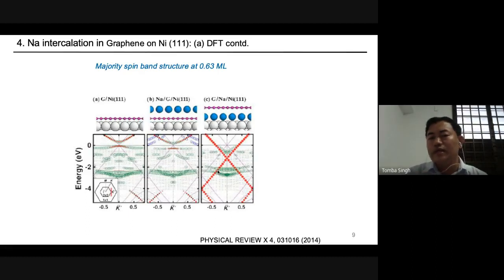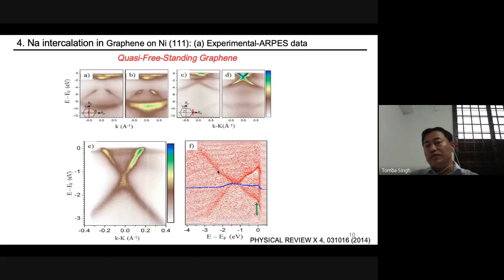Okay, we can see this from the DFT theory, but can this Dirac cone really be observed experimentally? This is a signal of free-standing graphene. Is it really experimentally available or not? So we have to see the band structure using angle-resolved photoemission spectroscopy.